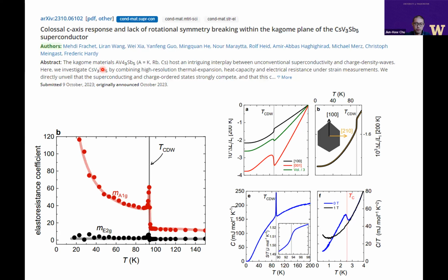So for iron-based superconductors, it is more important, because in iron-based superconductors, if you're aligning along the iron arsenide direction, it's B1G. If you're aligning with the iron bonding direction, it's B2G. But for the hexagonal symmetry point group, it actually doesn't matter because the anisotropic is a two-dimensional irreducible representation.